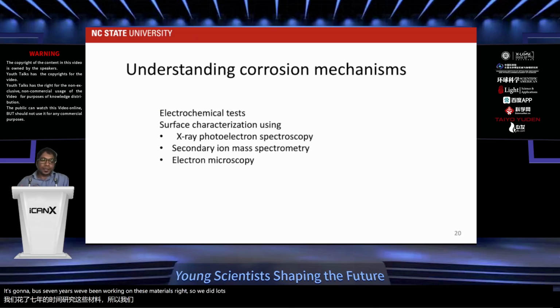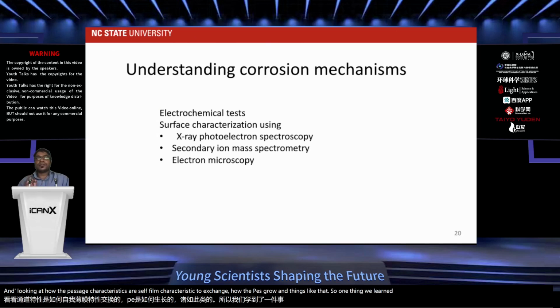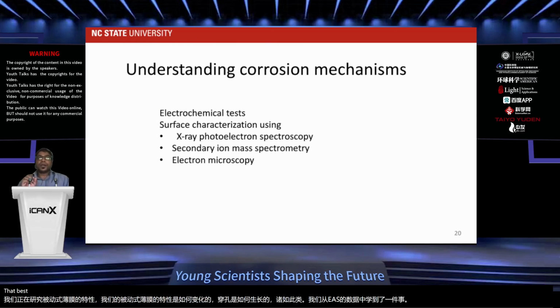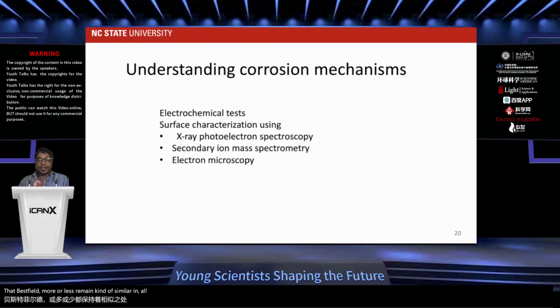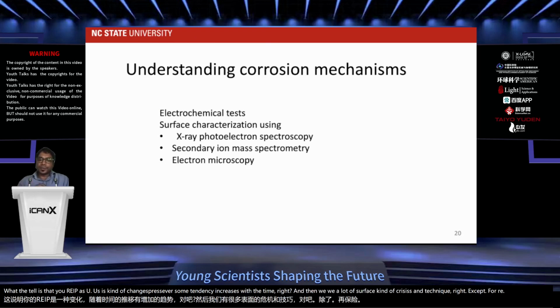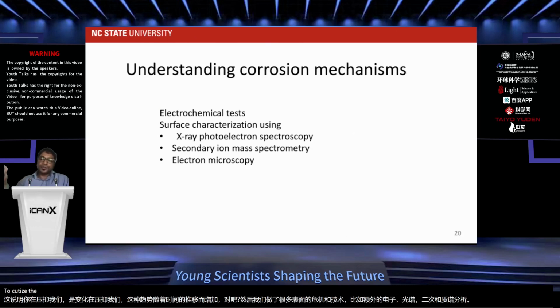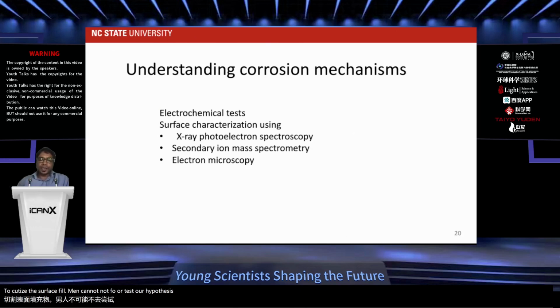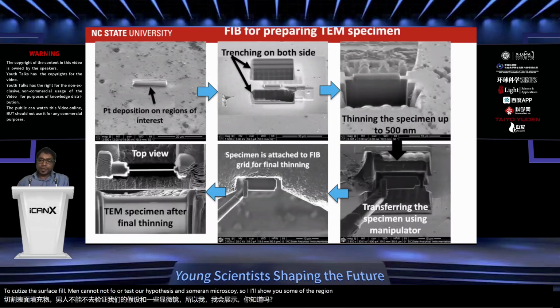So we did lots of EIS, long-term EIS tests, like month-long EIS tests, and we're looking at how the passive film characteristics or surface film characteristics change, how the pits grow and things like that. One thing we learned from the EIS data is that the passive film more or less remains similar in all these different alloys. One key contributing factor was the charge transfer resistance. What that tells us is that the repassivation tendency increases with time, right? And then we did a lot of surface characterization techniques like X-ray photoelectron spectroscopy and secondary ion mass spectrometry to characterize the surface film and test our hypothesis, and some electron microscopy. So I'll show you some of the results coming from the electron microscopy.